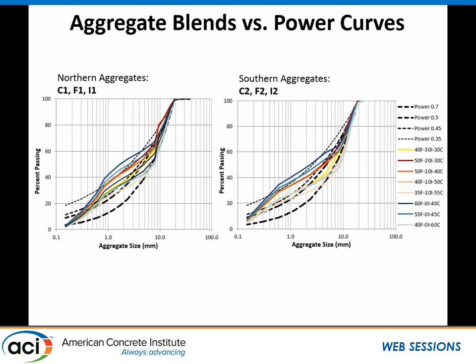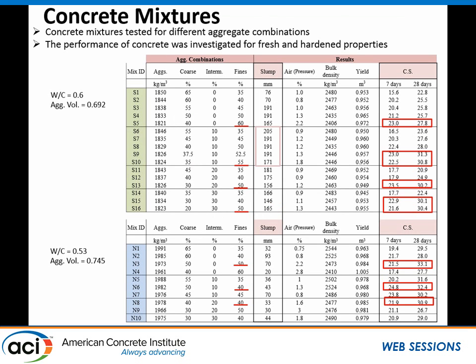If you take that, then for northern aggregate, 40% fine, 10% intermediate and 50% coarse, the other one below it, is being used. So, again, running those experiments and models helps you find the best blend, which we have done. So 10% intermediate is being used because of that. Southern aggregate mixtures are produced with a water cementitious ratio of 0.6. The volume of aggregate is held constant at 0.69. Northern aggregate is produced with a different water cement ratio with a closely similar volume of aggregates.